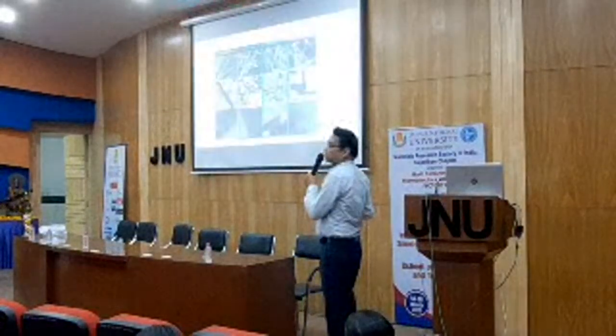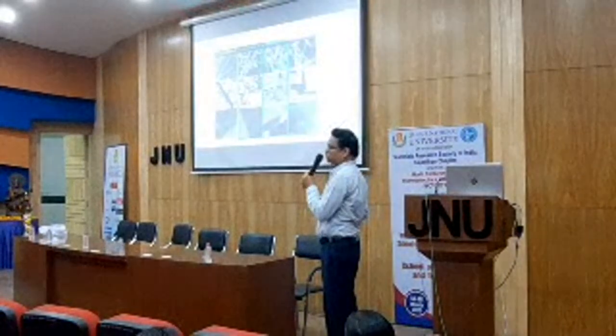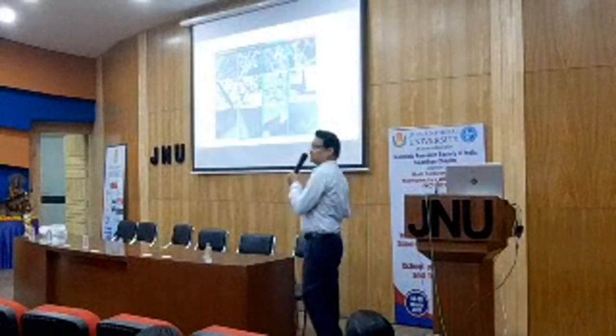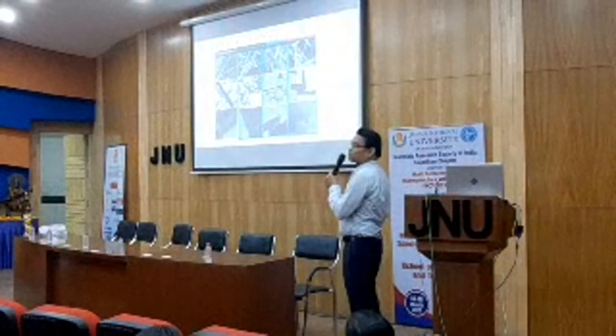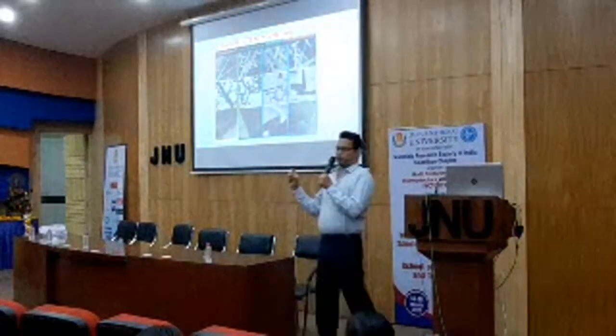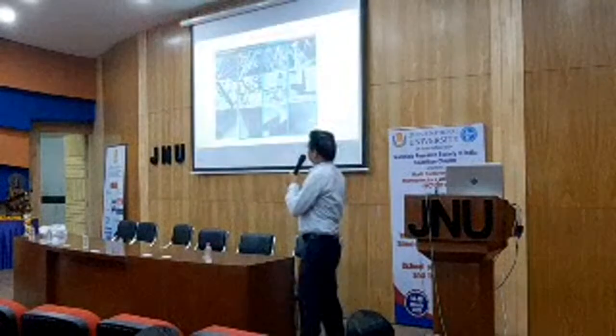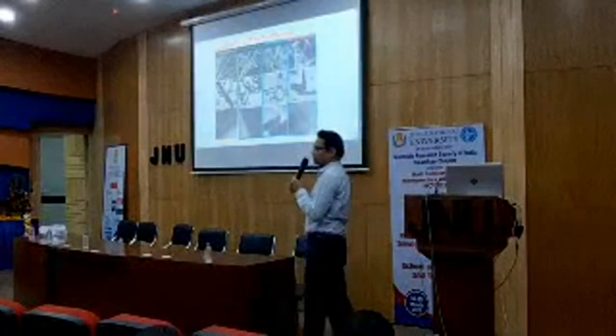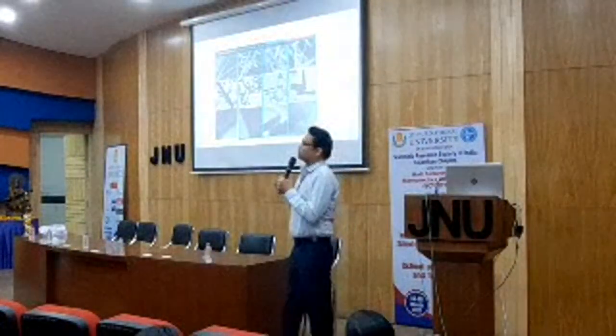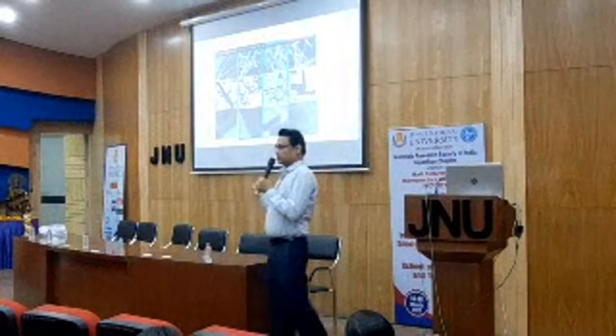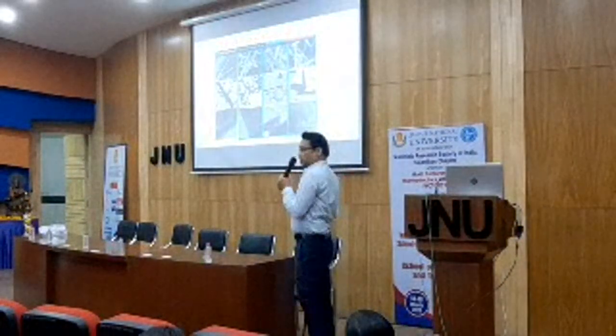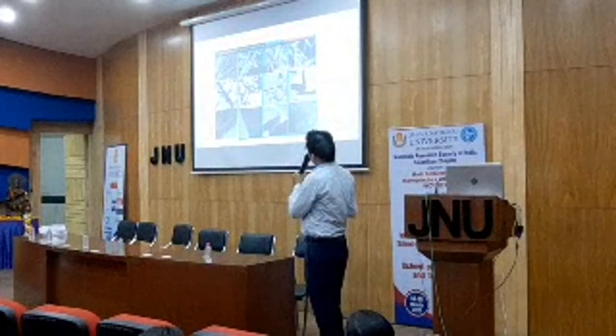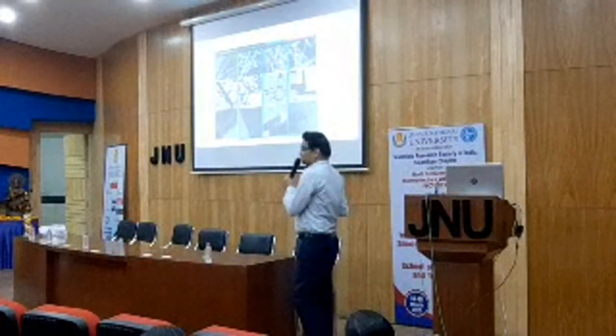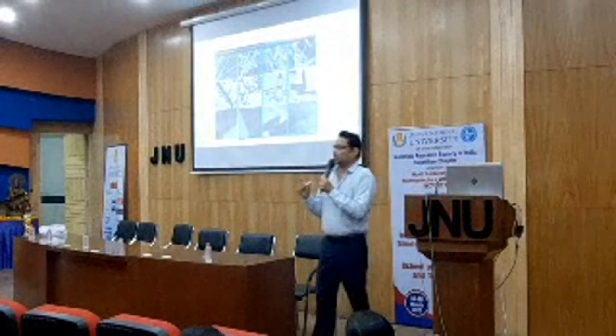Some end up with nanotubes, graphene-doped bismuth telluride nanotubes. Some have the chain structure, and each and every morphology has a direct effect on the ZT value, right? If you take pure nanowires, the ZT value is different, because the electrical conductivity and thermal conductivity phenomena for this nanowire are different from nanotubes doped with graphene. Similarly, the graphene-doped chain structure has different phenomena occurring at the peak property.